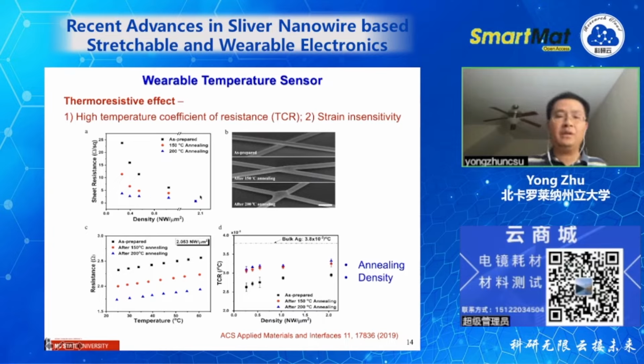So let's talk about this. We look at a couple of things. One is annealing. We have this percolation network, as prepared, held together basically by van der Waals interactions. Then we can anneal them. When we anneal them, we found that the TCR, the temperature coefficient of resistance, actually increases with annealing. We found that 200 degrees C is the best. Also, the nanowire density matters: an increase in density also leads to a larger TCR.